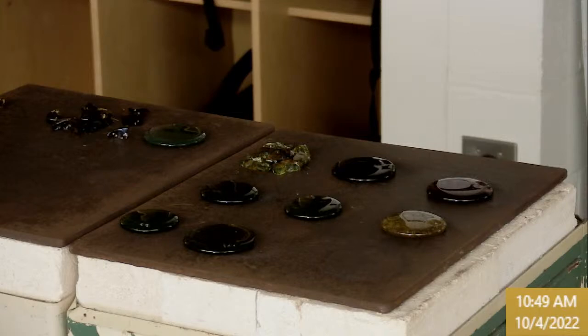But keep your eye on the timing as they're making their preform, putting it into a blow mold, blowing it into the bottle, moving it on the hot conveyor to go off to the annealing oven or the annealing leer. The timing, as soon as they remove it from the parison mold, it slams shut and plop goes in the next glass. Crazy. But the same features, you'll see annealing, stress cracking, but now in something mass-produced and more practical: glass bottles.